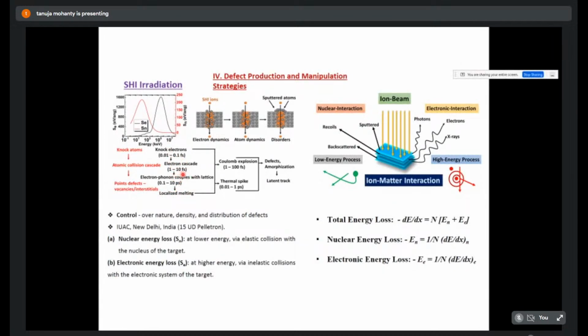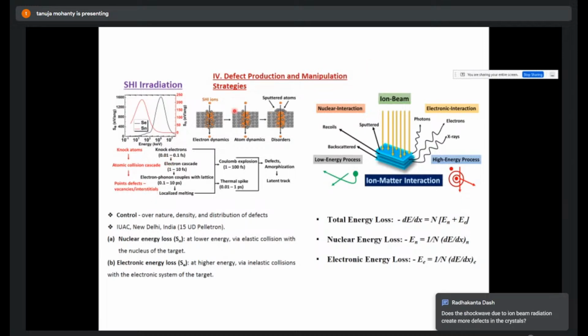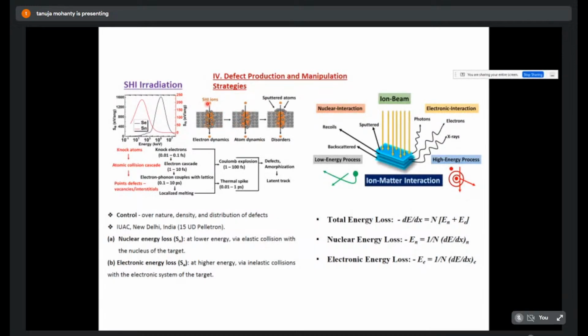That knocks the electrons and produces an electron cascade, and that happens in about 10 picoseconds. After getting so much energy, the lattice naturally converts the energy to heat. Once the lattice has heat, if it is a good conductor, the heat will pass through. If it isn't, that area will get defected, meaning it will melt or something will happen. Everything occurs in a very short time, 10 to the power minus 14 to minus 12 seconds. So the lattice naturally gets defects, and this type of defect can be produced.